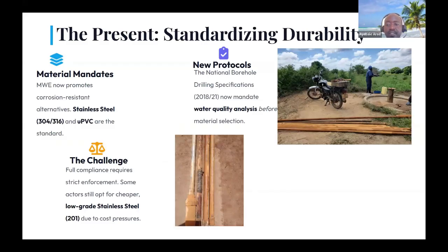Looking at the present and standardizing, we appreciate from the previous presenters that some of the causes of corrosion, the key culprit, is the indiscriminate use of galvanized iron riser pipes. Crucially, they were used irrespective of the local groundwater chemistry, in areas with aggressive water where these pipes quickly failed. The results were devastating, with high non-functionality rates and contamination of water, where we have a lot of red water coming out of bores in the mornings.